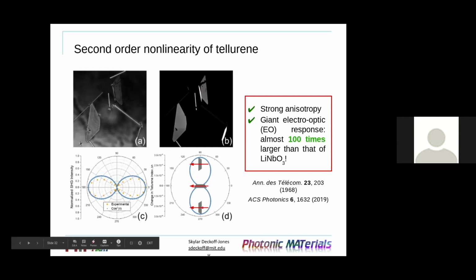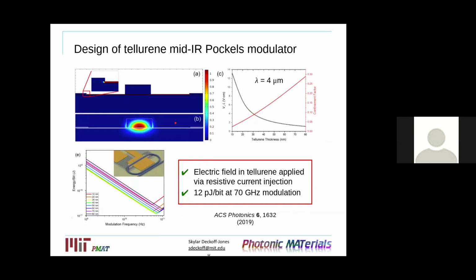And so we want our electric field to be perpendicular to the length of our trapezoids. You can determine the exact crystalline orientation of these trapezoids through Raman spectroscopy, but we found that quite uniformly the chains run along this direction of the trapezoids across, as the shapes are quite uniform for many of the flakes. So with this in mind, we can then set out to design our Pockels modulator and again optimize its performance.